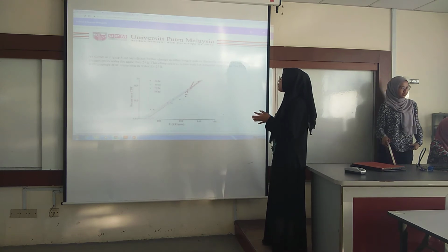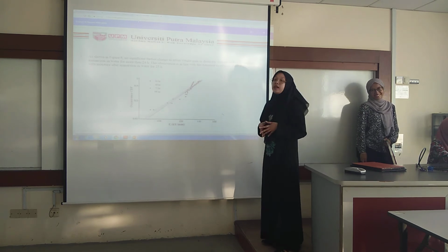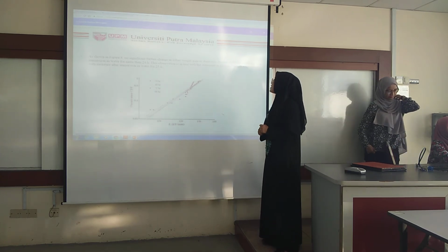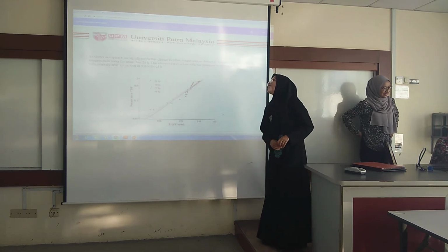As shown in figure 8, no significant further change in either weight gain or dielectric constant of PI was observed after immersion in water for more than 24 hours. This observation is in line with the statement in the reference that PI is saturated with moisture after immersion in water for 25 hours.